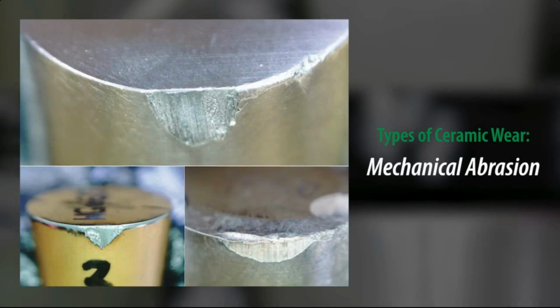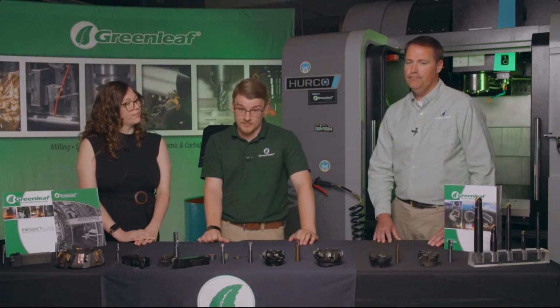The composition of the material being machined is more likely to have more strength and hardness variation between the material's main phases. The hardness of the cutting tool may not be sufficient compared to the micro hardness of certain phases of the workpiece material. This could result in too much heat being retained in the cutting zone, thus causing the extreme abrasive wear. Another option is that there is actually aggressive chemical wear, which can resemble mechanical abrasion.